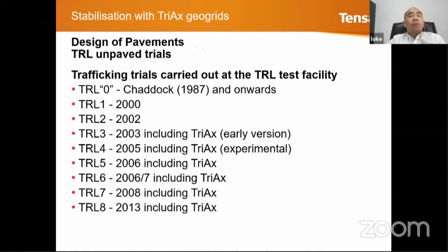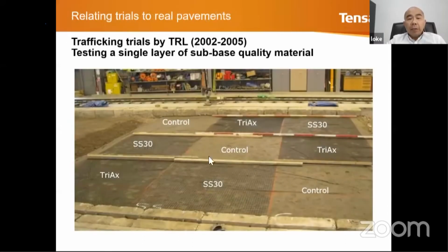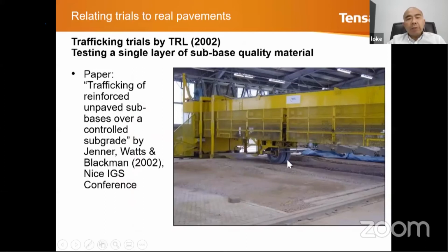And then we go into a full trial, which we call the TRL, which is in the UK. You can see a lot of sections that we have done, stiff geogrids and different kinds of geogrids. I've shown these particular facilities for you, and there is a lot of literature and publications of these tests. Okay, and these are done generally at 2% CBR, which is about 50 kPa in terms of undrained shear strength, and the thickness of the fill material above the geogrid is about 300 millimeters.